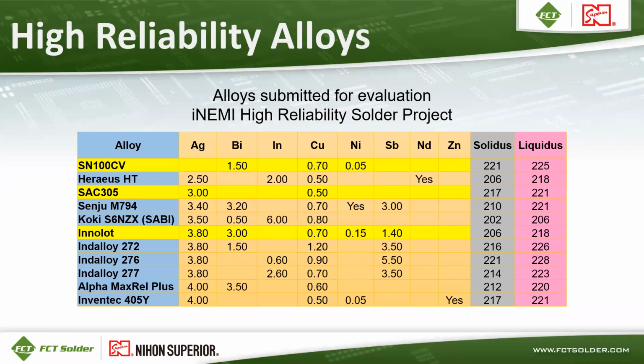These are alloys that were submitted to an iNEMI high reliability solder project, and I've highlighted 3 rows in this table. The first row is SN100CV alloy, which is composed of tin, bismuth, copper, and nickel. Then there's SAC 305 highlighted for comparison as the baseline alloy, and that has 3% silver and 0.5% copper, as you all are aware. And then there's Innolot alloy for comparison, which has silver, bismuth, copper, nickel, and antimony. So that's a fairly complex alloy, but it does hold up to under the hood applications for automotive electronics. And that's sort of become the industry standard for under the hood applications.